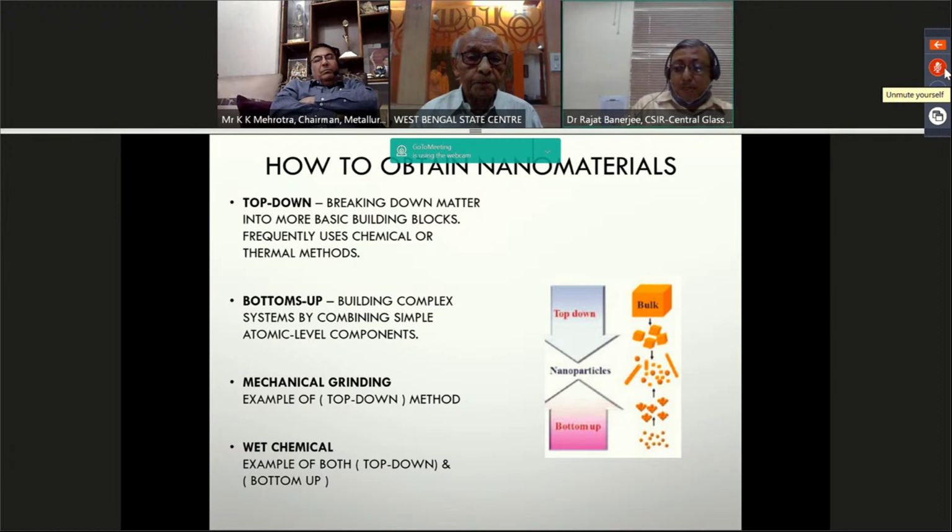Now, before I go into my next slide, I have a little story which I want to share with you. Long time back, when I was a PhD scholar working under Dr. Sarkar, he had a project given to him by DST, and the project name was quasi crystal. In that project, we were using vanadium pentoxide to find the quasi crystal material. The vanadium pentoxide particles were ground in a very high energy ball mill. After around 20 or 30 hours, in place of the particle size going down, the particle size was increasing. We got the impression that as the particle breaks down, due to van der Waals forces, it gets agglomerated with another particle and the size increases.